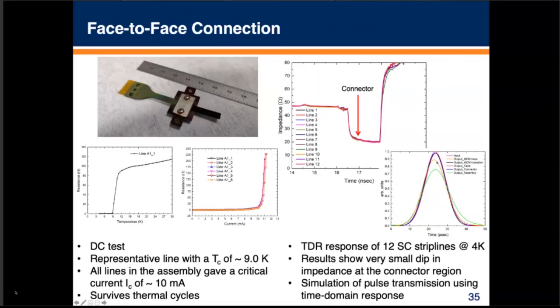And then if we cranked that through a simulation model, you could see what the degradation was. Basically this is a single flux quantum-like pulse. So here's the input. And then once it came out of the whole entire thing, you can see it was degraded by about 30% in this particular case. But this is a very high frequency pulse, right? These are tens of picoseconds here.